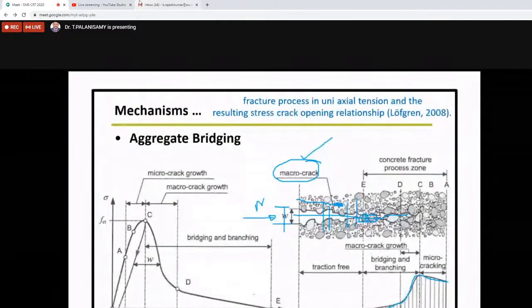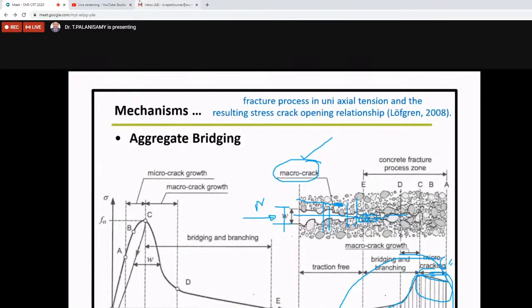Now, when the stress in the concrete is equal to the stress in this profile, which may be straight, you can develop the stress-strain or bridging stress of the fiber reinforced concrete in the system. Due to this, both macro cracks as well as micro cracks are possible. If we want to increase this length also, that is very good. For that, the aggregate size is also a very important factor for this aggregate bridging mechanism. Simply we can say the crack is going on, and in between we have the aggregate; this aggregate bridges the crack. That is called aggregate bridging.